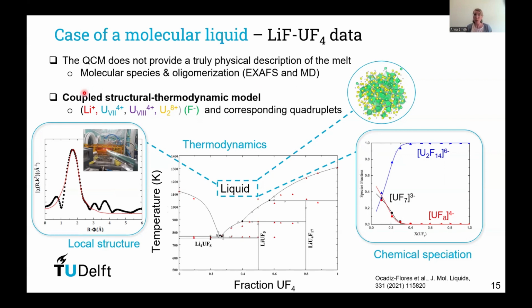So what we have done is to introduce a bit more structural complexity into this quasi-chemical description by introducing some cations with a certain coordination. We knew for the lithium fluoride, uranium fluoride system that we form at low lithium fluoride content mostly 7-fold and 8-fold coordinated uraniums.